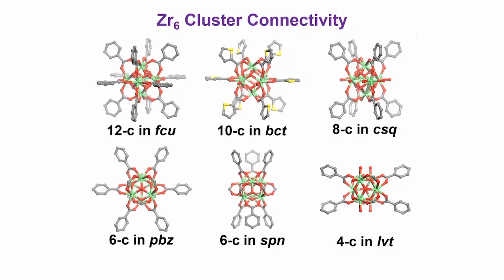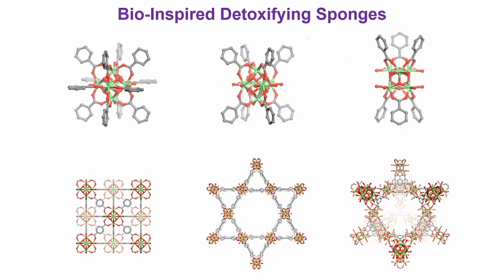And I'm only putting the even numbers because those are the ones you could actually predict. Nowadays, you could make a 7, a 9, an 11. I don't know how you could actually predict those. We got the 7 recently, and it was serendipitous. We couldn't have design rules for making, at least in my group, I don't know how, a 7 connected. We made it by accident. But at least with the even numbers, you could now precisely predict these materials. And we were able to make the 12, the 8, and the 6. You have UiO-66, NU-1000, and MOF-808.